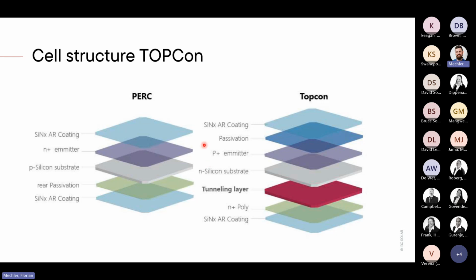The reason is when you are looking at the structure of PERC, and then at the structure of TopCon, you see, okay, the coating is more or less the same. Then the emitter, it's the same. Okay, not completely the same, but here it is an N positive emitter. Here it is a P positive emitter. Then you have a substrate in the middle of the cell. Here it is a P silicon substrate. Here is an N silicon substrate. Then you have a rear passivation, more or less here. And then you have again coating on the backside. So we have only two layers which are additional. So you have the tunneling layer on it and the passivation on the front. And you see the cells are really near to a PERC cell.